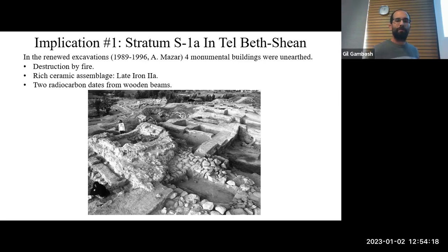They're clearly destroyed by fire. And they had a very, very rich ceramic assemblage, which is late Iron 2A. But the problem is that for absolute dating, we didn't have radiocarbon that could help us date the destruction of these structures. They did take two radiocarbon samples, and they were published in the past, but they were taken from wooden beams that were used to construct these structures. So wooden beams, of course, they only give us the date of the construction, and of course there's the old wood effect. So both of them gave us completely different results, about 200 years difference between the two samples.